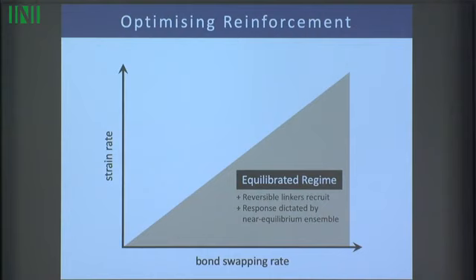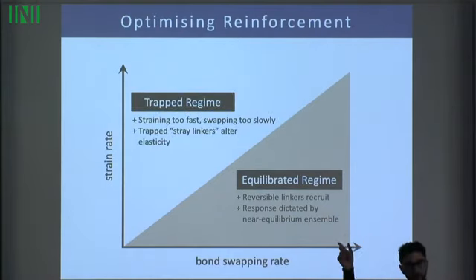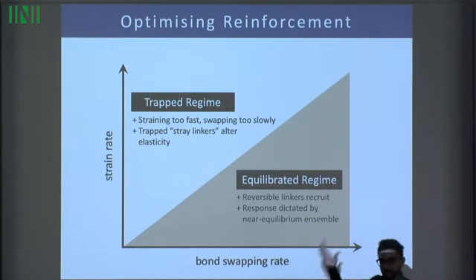If I'm on the other side, I'm in what you might call a trapped regime, and this is where I strain so quickly, and the bonds are rearranging slowly relative to that, so stray linkers that are away from the equilibrium ensemble might dictate more strongly the mechanical behavior. Okay? And so I don't have the time scale provided to those things to let them rearrange and to equilibrate into a better position. So we want to be here because this is actually the region where you get the best clustering, but you also don't want to be there at the same time because those bonds might be too weak to actually bear mechanical force.